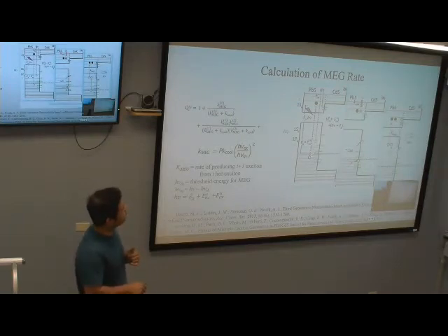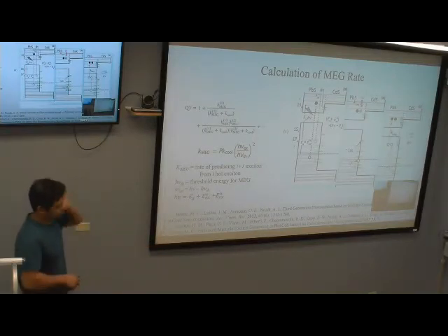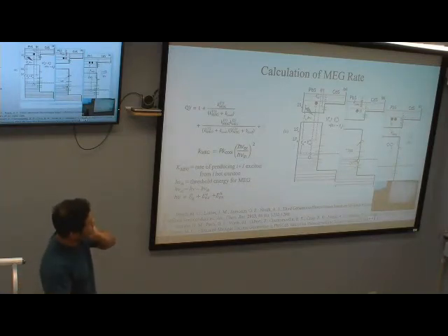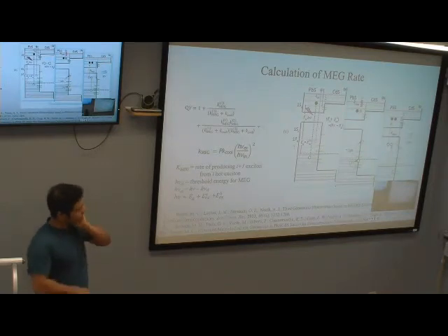As a result, this slows down the relaxation process, so there is enough time for impact ionization. But if it's excited close to the band edge here, there is no trap state coupled with this interfacial state, so the hole relaxes faster and won't create the multi-exciton. So it's giving an example here of 3 different scenarios.